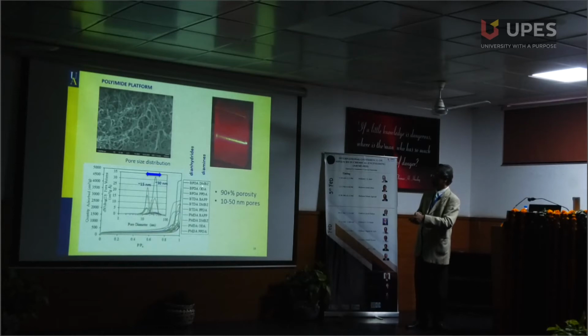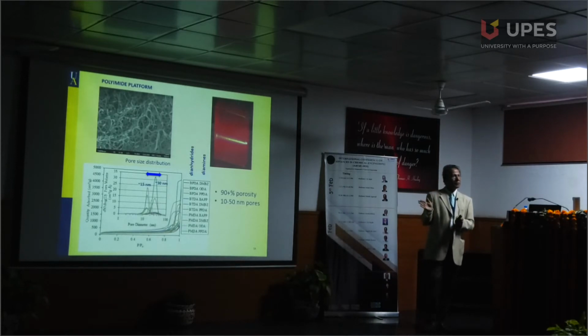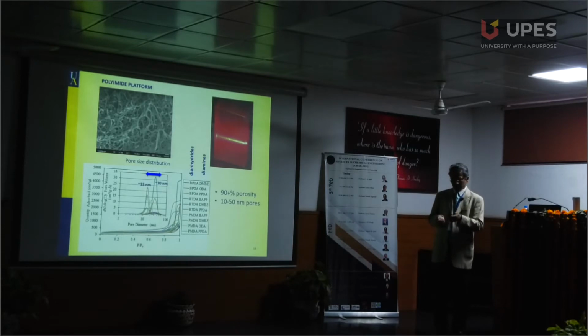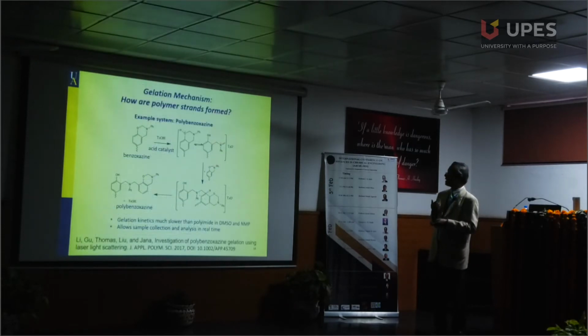Combinations of diamine and dianhydride, you can in fact tailor the pore size distribution with a most probable pore size of 50 nanometer to 30 nanometer or so. Okay? So chemistry helps us, and making chains stiffer, we can get narrow pore size. Making chains a little bit more flexible, we can open up the pore size. But that doesn't solve the problem completely.